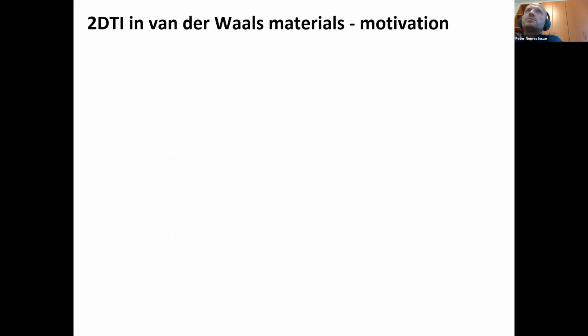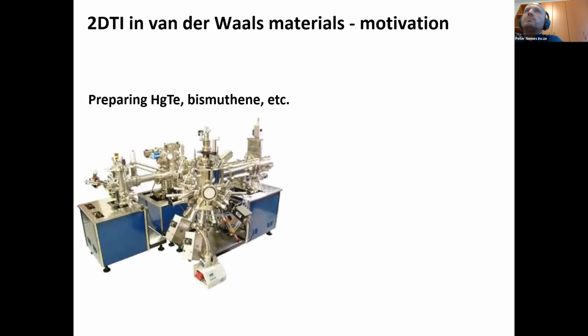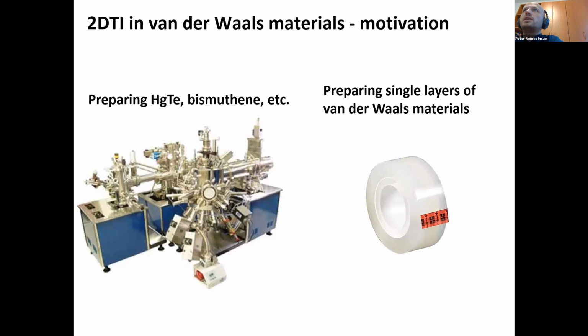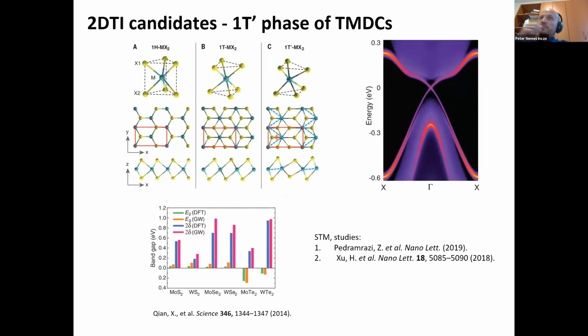The main motivation here, again, is just doing experiments in a simple way. For mercury telluride, the prototypical quantum spin Hall system, or this bismuthene and stanene, you need very elaborate UHV molecular beam epitaxy systems to make these. So the accessibility is not very good for a lot of experimental groups. On the other hand, working with van der Waals materials, you could jokingly say that all you need is some Scotch tape and you're done. The most prominent van der Waals topological insulator family would probably be the 1T prime variant of the transition metal dichalcogenides, so molybdenum sulfide, selenide, tungsten sulfide, selenide, and so on.